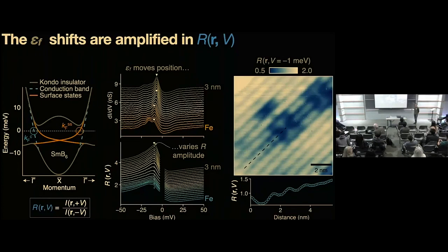The scattering length suggests that the quantum oscillations signal only moves about 10 nanometers before it scatters, whereas it should really be moving more than 100 nanometers to form cyclotron orbits. So whichever way you look at this, the quantum oscillations are definitely unconventional. Whether you're applying a semi-classical notion or something more exotic like these Kondo holes, either way, it's not perfect.